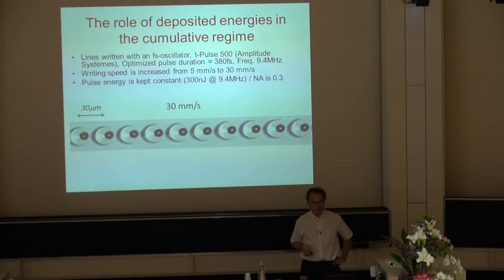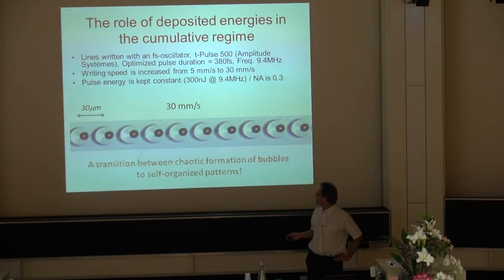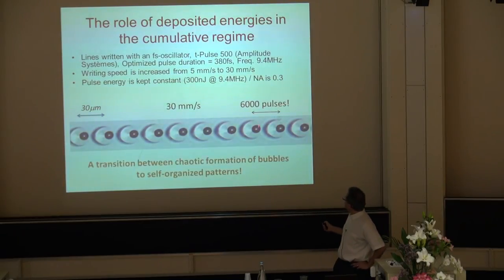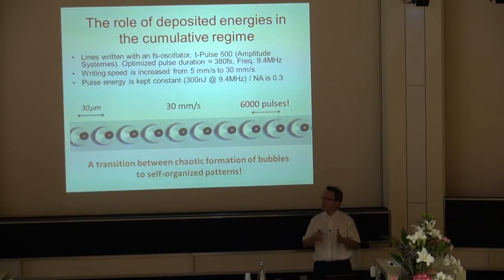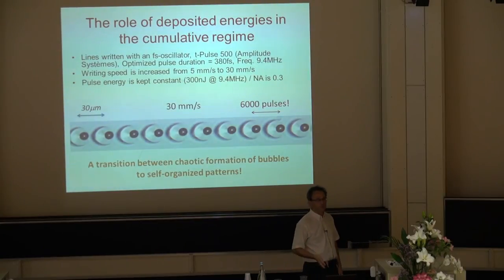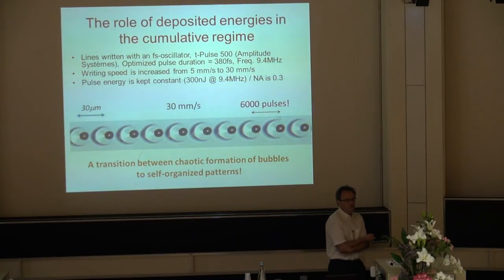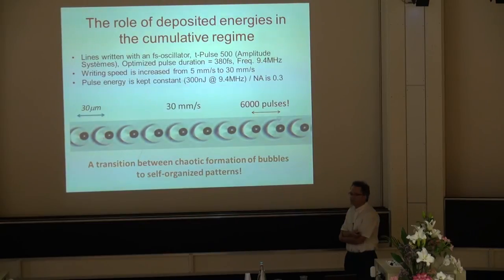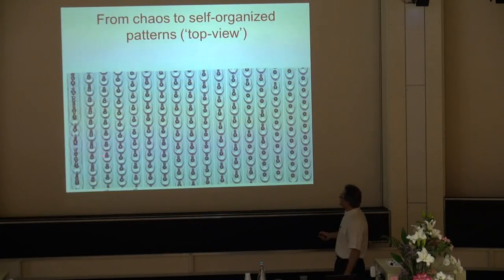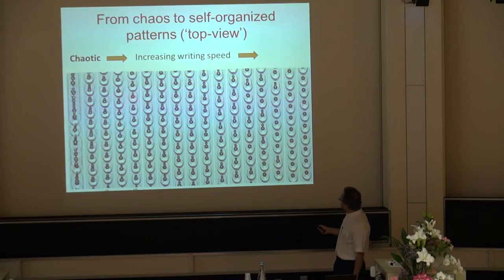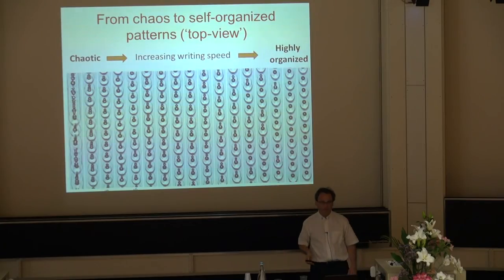So it's extremely irregular, okay? In particular, because in between these bubbles, I have a lot of pulses, 6,000 pulses. So even if I have some noise in the system, this is in a way self-regulating. It's a very interesting phenomenon where you have the physics driving the periodicity of the structure. And you see here, we start from a chaotic regime, and then we keep on increasing the speed up to a point where it becomes highly organized and perfectly regular.